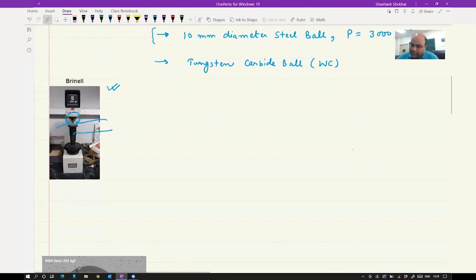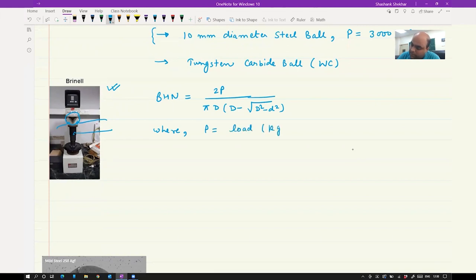Okay, so this hardness measurement in this case can be given as a BHN, which is Brinell hardness number, and it will be given as 2P divided by pi D times D minus square root of D squared minus small d squared. Okay, where P is your load and it is in kgf, D is your indenter diameter, so here ball diameter, which is typically we use 10 millimeter. Okay, and then small d is your diameter of indent impression.